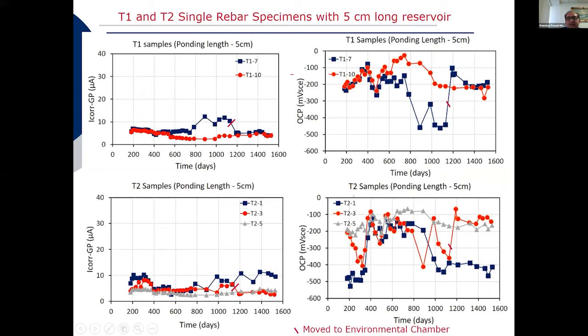For the T2 sample that you see here on the bottom, the T21, the blue one, was not moved into the environmental chamber and had a behavior with a little bit of oscillation initially, then it plateaued, and then it started to increase after 900 days, and it has been oscillating and relatively remains at a value of about 10 microamps. The potential, again, corroborates that it was active. It became less active, if you will, with a more positive potential, but then it decayed again.